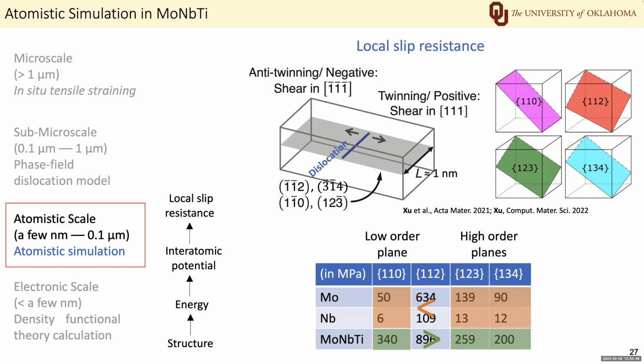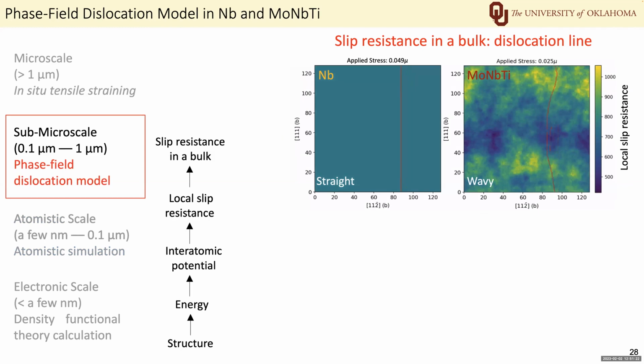However, in molybdenum niobium titanium, the opposite is true. So this is unexpected. On the other hand, these slip resistances are local and evaluated based on a short dislocation. So how about the slip resistances of a long dislocation in a bulk material? To answer that question, we use the phase field dislocation model to calculate the slip resistances of the long dislocation in both pure niobium and molybdenum niobium titanium.